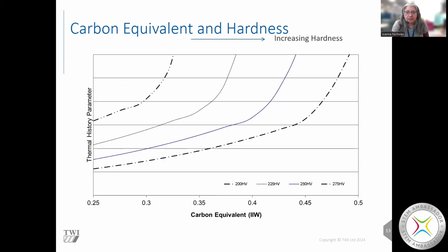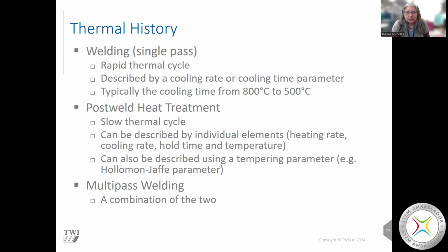The carbon equivalent leads to a particular hardness with changing thermal history parameter. And so, for a higher carbon equivalent, we can expect a higher hardness for the same thermal history. And we kind of end up with that as our basis of what's going on. So when we're thinking about welding, we think about a single pass weld. That's just one weld bead deposit.